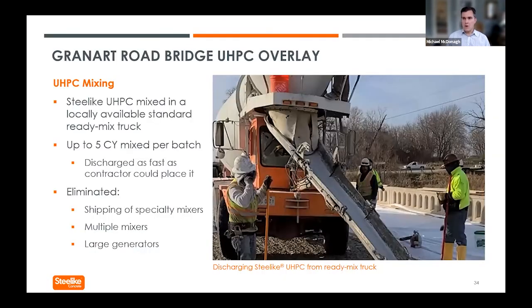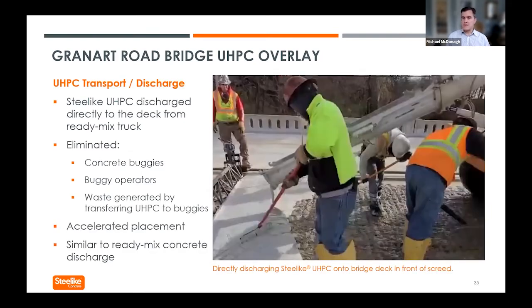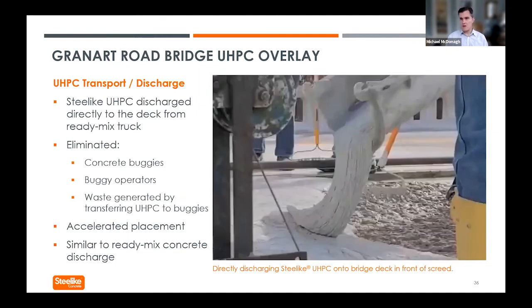For the Granart Road overlay, the UHPC was also mixed in a ready mix truck, which provided a major advantage besides the volume and eliminating of specialty mixers, and that was the ability to discharge directly from the ready mix truck onto the bridge deck. So you're eliminating concrete buggies, you're eliminating the laborers to move those buggies, and you're eliminating the waste that gets generated every time you transfer material from one vessel to another. This accelerated the placement and also has an added advantage of being similar to ready-mix concrete discharge.